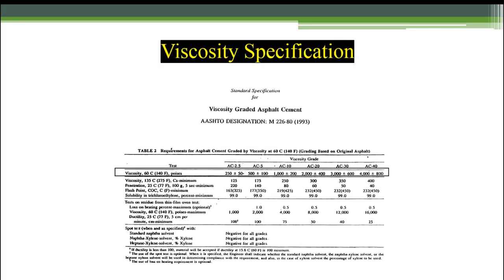So the next kind of standard specification that's out there, particularly if you're looking at RAP and original pavements, was AASHTO M226, which was the viscosity graded asphalt cement specification. And I lined out that first line. First thing to note is that first line in the spec is the test is done at 140 degrees Fahrenheit. So now at least we can kind of make an analysis, how often do we get to 140? Well, probably the middle of the summer, right? You get 5, 6, 7 days, real hot days in a row, or it doesn't cool off at night. You can get pavement temperatures up to 130, 140 degrees, right? The middle of the 5th day or 6th day.